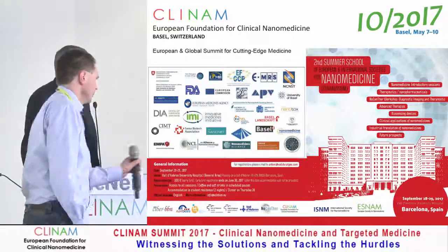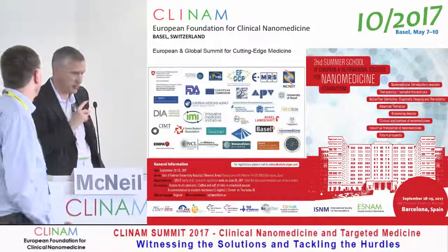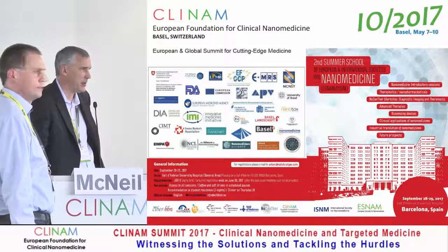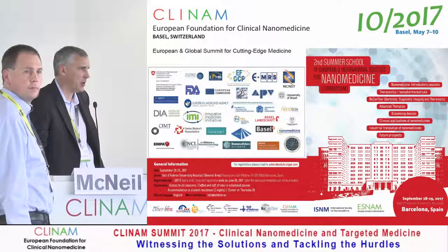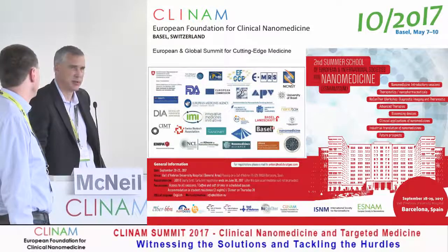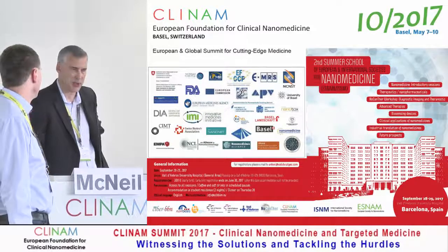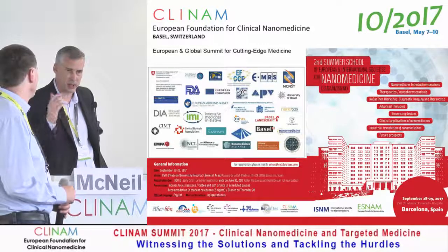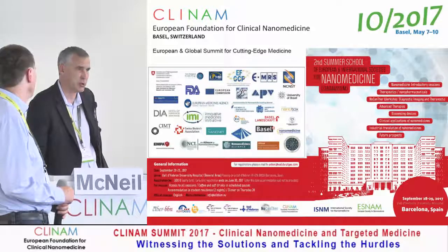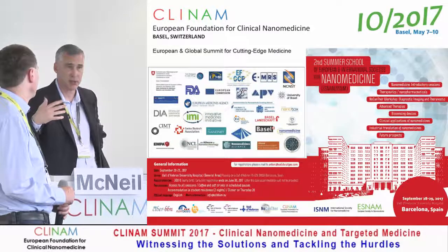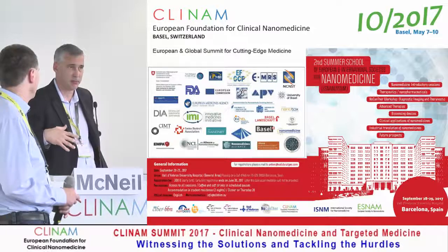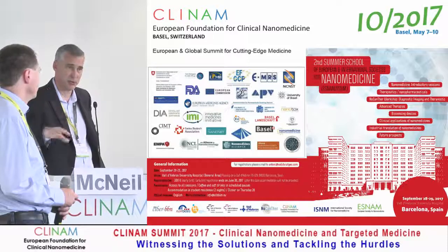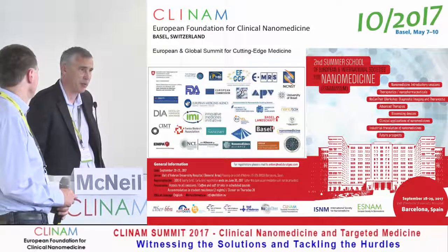That's a great question. So we have a number of them. I wasn't able to go into depth in there. But what we see is that you cannot assume that they're equivalent, even between two liposomes, for example. So there's assays available where we put it into blood, for example. If it's a lipophilic molecule, that's probably one of the best ones. Otherwise, it's very difficult to track it. It'll often just pop out unless you tweak it, if it's in a liposome, a hydrophobic molecule.